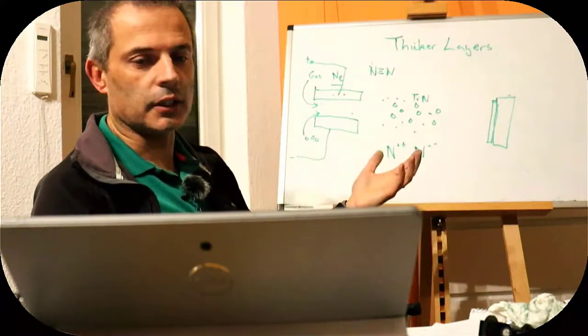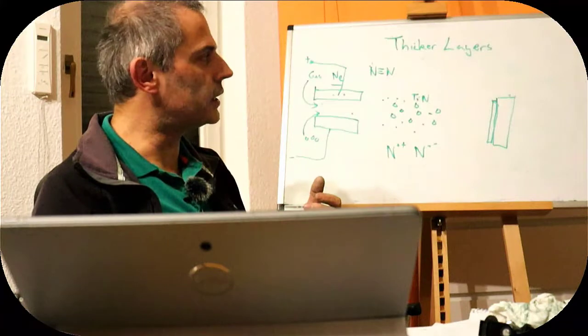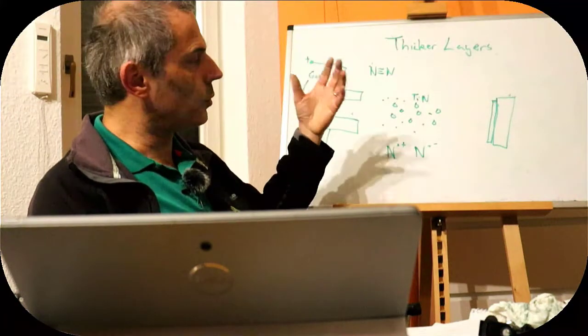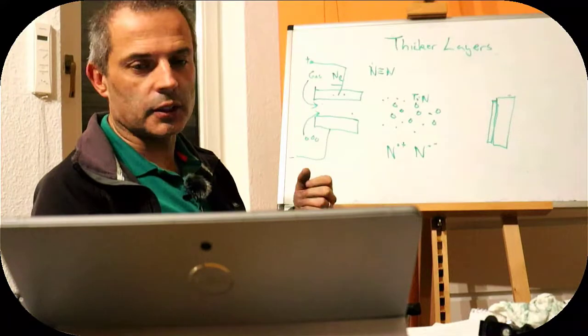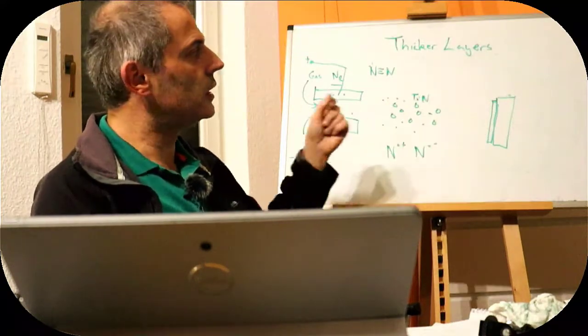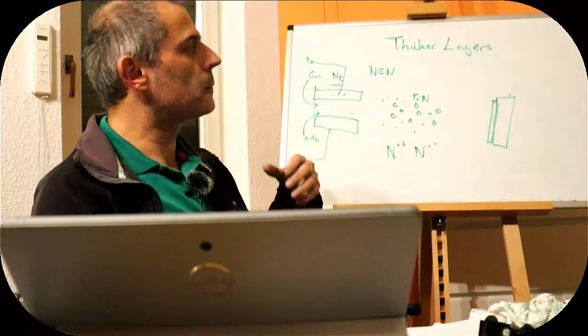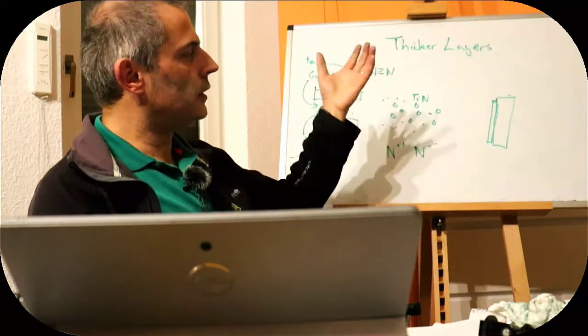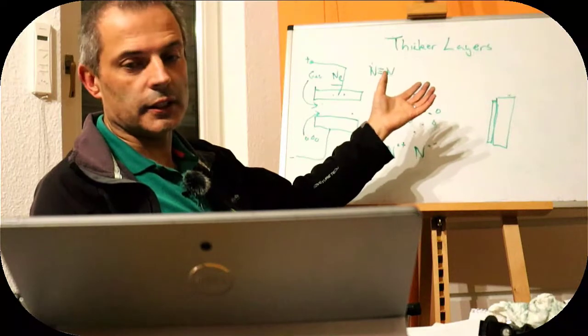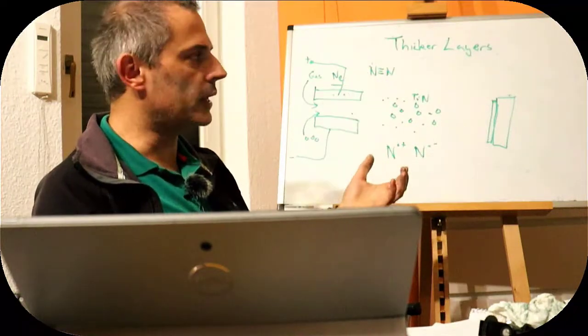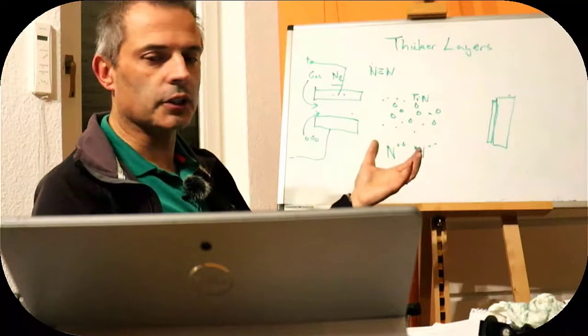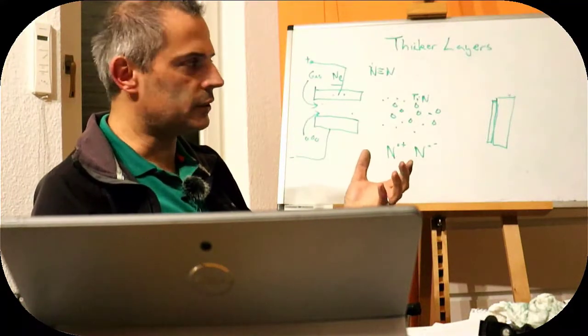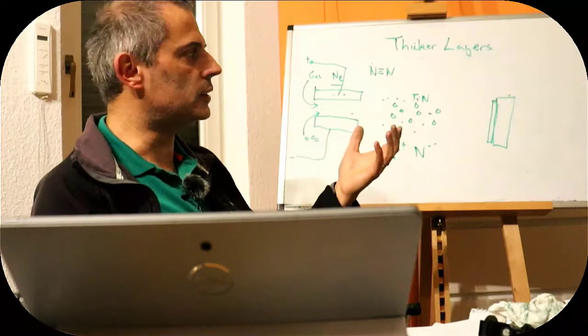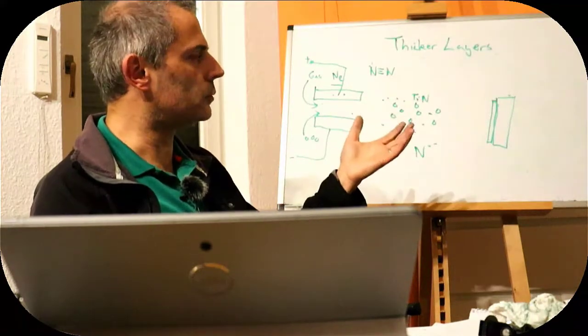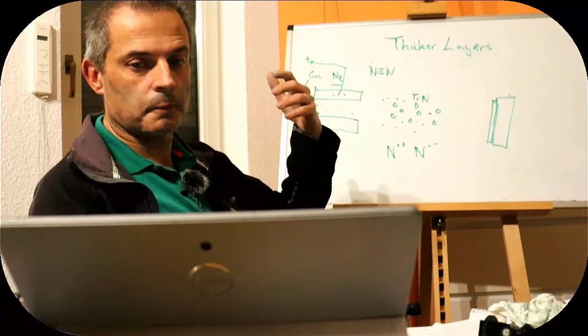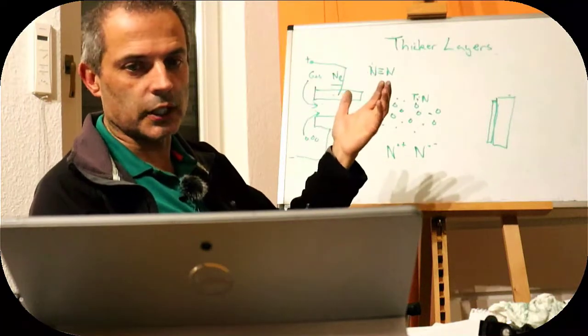The blade is typically an alloy, could also be pure titanium, and the problem there is we don't want to melt it. The melting point of titanium dioxide is way higher than the melting point of the metal, and we want to coat it. We need to coat it with an insulating layer, because the blades that are inside the combustion chamber are going to be exposed to extremely high temperatures, and they're cooled with an internal flow of air or water, depending on which ones they are, and they need an insulating layer to stop the surface from getting too hot.